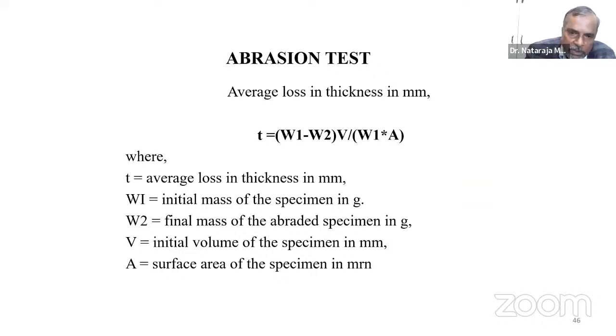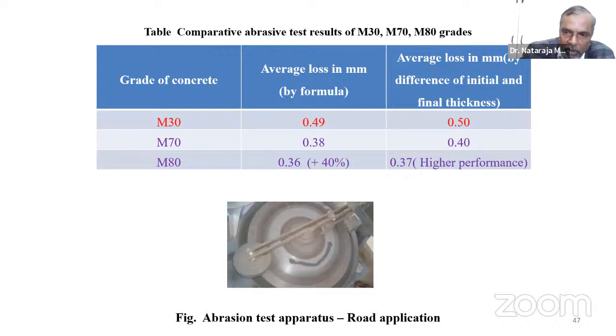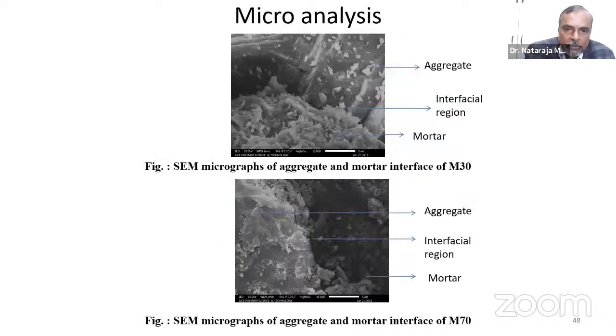Also, we have done the abrasion test, and I will share the result with you. For M30 concrete, the wear and tear on the surface for a given operation of the testing is about 0.5 mm. But when it is M70 or M80 concrete, the wear and tear is quite less. To the extent of about 40%, the wear and tear resistance of the concrete can be enhanced. The average wear, in fact, decreases. So this is where the wear and tear resistance, one of the important requirements for a pavement concrete, is also being examined in our studies.